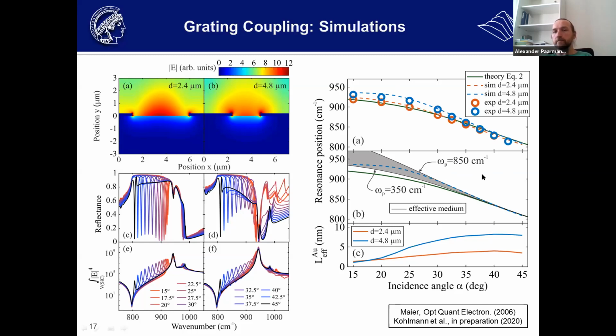To estimate how much of a plasmonic contribution you need, we included a Drude term in the silicon carbide dispersion as a simple-minded model. And we see that to reproduce the slope in the beginning, we need a relatively high number of carriers, but then the shape drops off and gets flatter towards larger momenta.